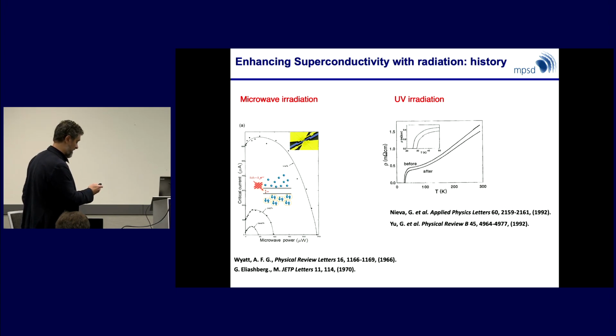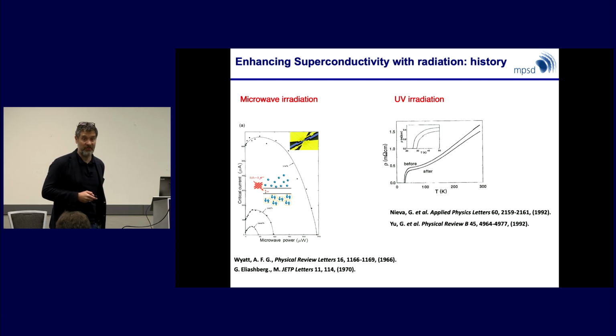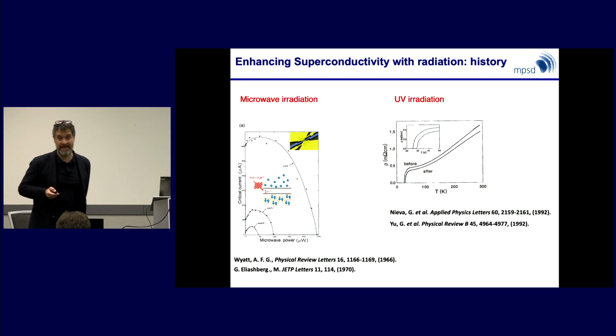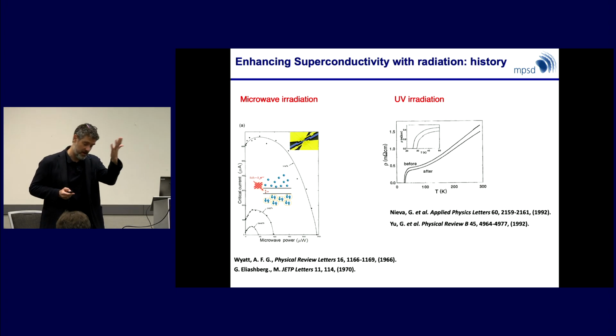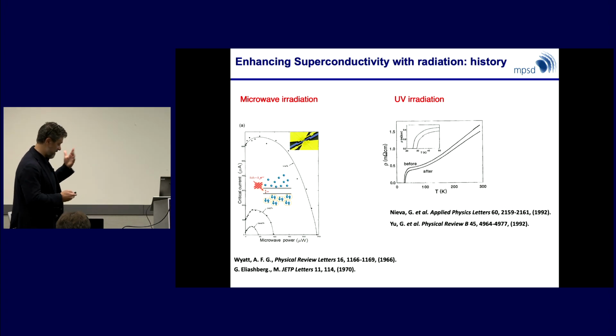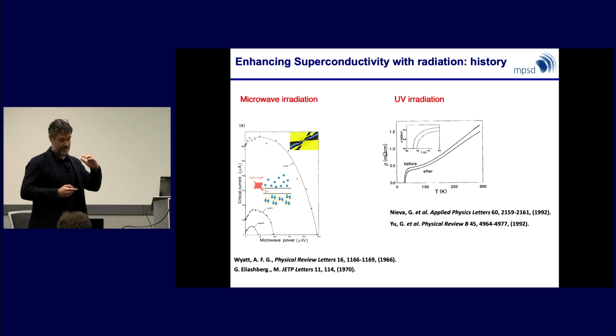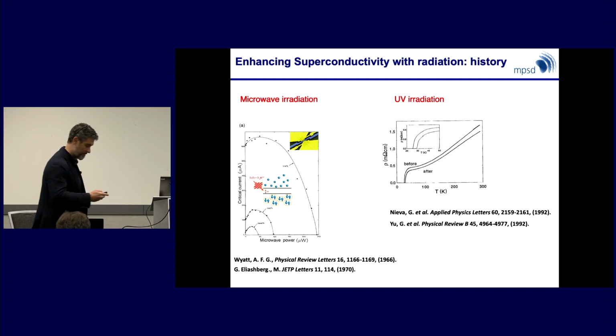There's also been a lot of other work where irradiation of cuprates, for example, in the ultraviolet, has resulted in enhancement. If you take an underdoped cuprate, you could observe transiently or in a metastable state the properties of the same cuprate at a higher doping value. But in these cases, people were not able to achieve effects that were not observed in that class of materials at the best doping.